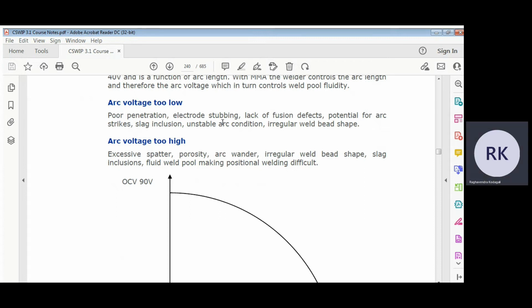If the voltage is too high, there will be more spatter, porosity, arc wandering. What is arc wandering? Arc will go here and there, left or right. Then irregular weld bead shape, slag inclusion, fluid weld pool making positional welding difficult. So almost the issues are the same in both cases.